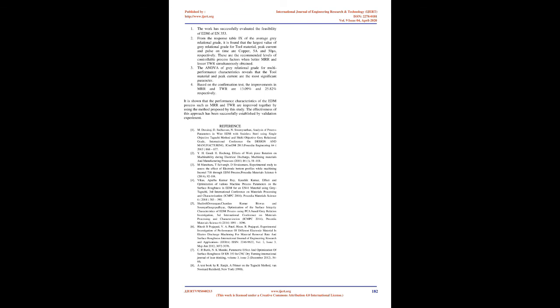1. The work has successfully evaluated the feasibility of EDM of EN353. 2. From the response table of the average Gray relational grade, it is found that the largest values of Gray relational grade for tool material, peak current and pulse on time are copper, 5A and 50 microseconds respectively. These are the recommended levels of controllable process factors when better MRR and lesser TWR are simultaneously obtained.